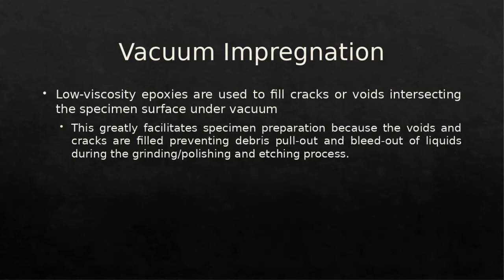With those cracks and all that stuff being filled, you have debris that will not collect, which would then pull out and push across your sample, scratching your sample. You reduce the risk of more bleed out of liquids, since you do use DI water, ethanol, and your etchants. So it helps in the long run. The better care you take for your sample after you section it, the more you reduce the risk that you're going to mess up the sample towards the end.